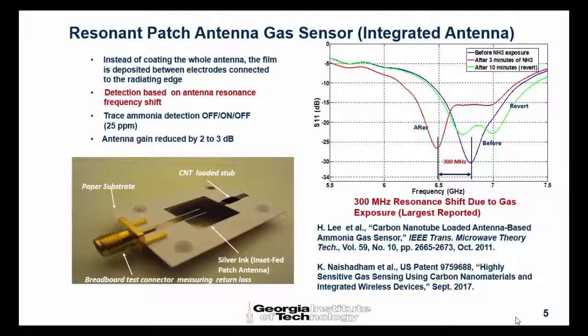So what we did is we took that chemi-resistive film and put it across a patch resonator. This is an RF kind of measurement. We have a patch resonator connected to a network analyzer to measure the reflection coefficient. At the end of the patch, we have a small stub with a gap, and we place this nanotube film across that gap. This has been reported in 2011, and we also got a patent on this last year.